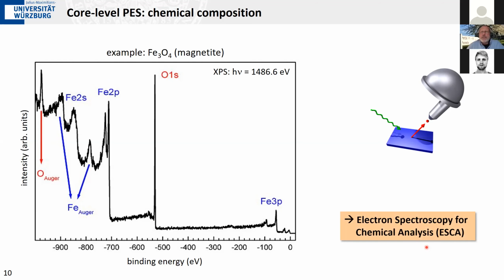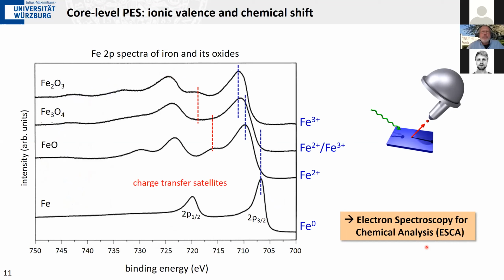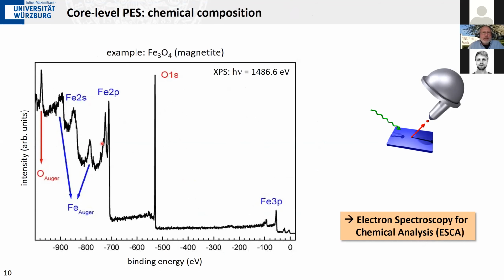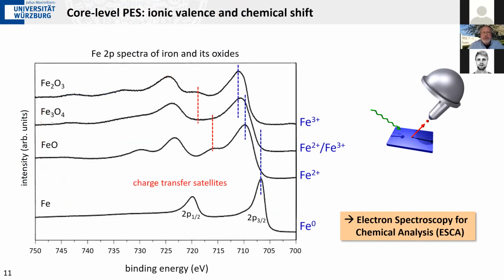So this is electron spectroscopy for chemical analysis, because that gives you chemical information. There is even more chemical information encoded than just in the binding energy. You can also say something about the local binding environment of your transition metal. And here I have shown you the iron 2p range, this part here, blown up to a finer energy scale for various iron oxides.